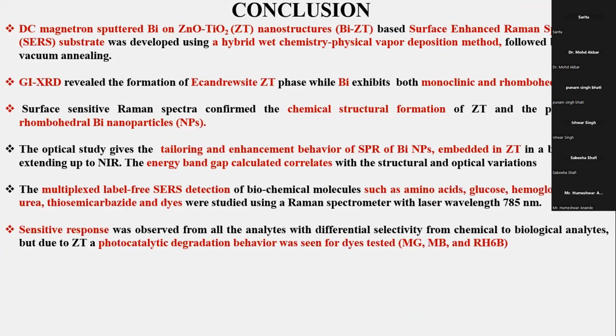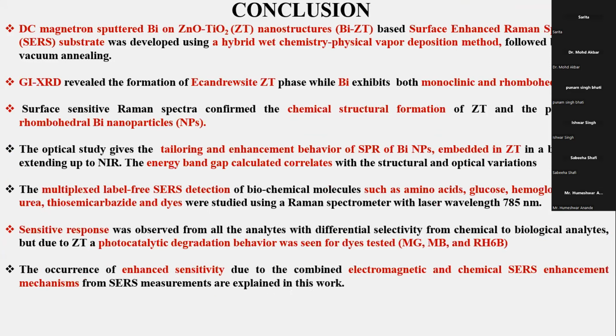Multiplex label-free detection of 9 molecules is done using a normal Raman spectrometer with a 785 nanometer laser. And the photocatalytic degradation of zinc oxide, titanium dioxide is seen. The occurrence of enhanced sensitivity due to combined electromagnetic and chemical enhancement mechanism is explained in this work.